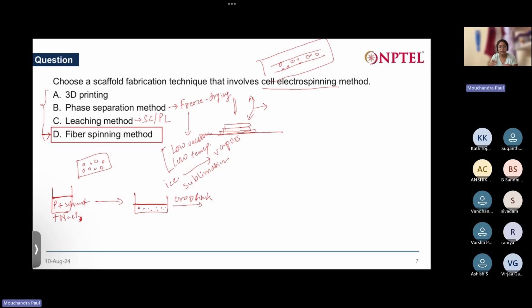What happens after cross-linking? The polymer with solvent forms physical or chemical bonds and solidifies, leaving the NaCl intact in its place. Whatever place it was in the solution, it gets set there. Then after cross-linking, you dip the scaffold into a bath of water. The water will dissolve out the NaCl crystals. When you remove it from water, you get a hydrogel block with pores inside. These pores are basically the previous residents of the NaCl crystals. So this is called the leaching method, and I just explained one type of leaching method, called solvent casting and porogen leaching.